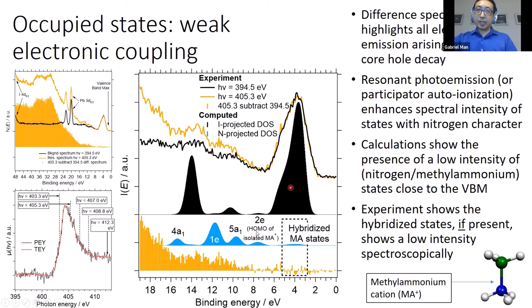To align the DOS calculations, we can at first align the iodine p projected DOS, because the valence band is mostly made up of it. And that automatically aligns the nitrogen DOS. Our calculations show that the molecular orbitals of methylammonium, which is this molecule over here, are pretty MO-like. So it seems to be rather unperturbed by its environment, but there's a little bit of intensity over here that overlaps the valence band. So this suggests that there's a presence of hybridized MA states.